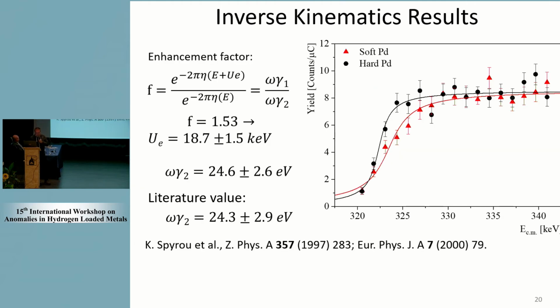And this is our result for these two foils, soft palladium and hard palladium. So you could say, okay, this is all the same, but it's not. One contains 50% less hydrogen, meaning that the resonance strength in that case is 50% higher. So that's how we determine this electron screening potential. What is also important is that the hydrogen distribution in the foil is fairly flat, so this is important for further analysis.